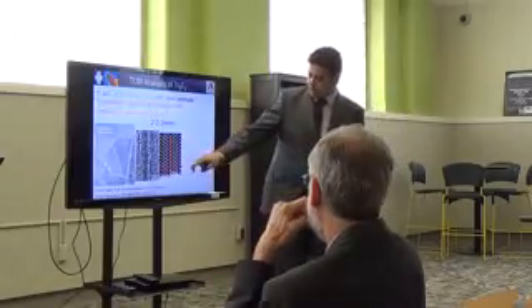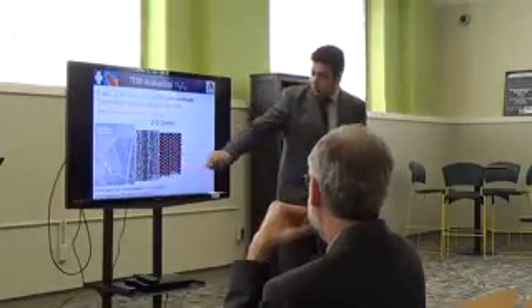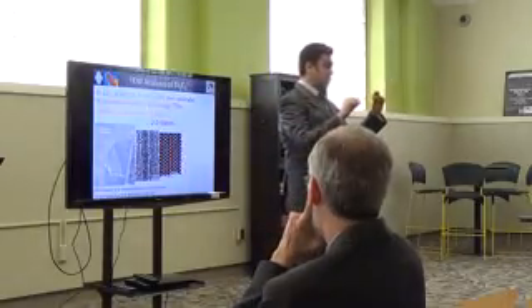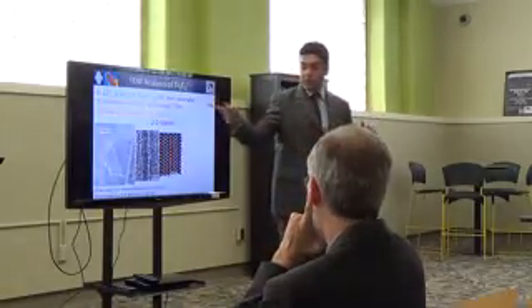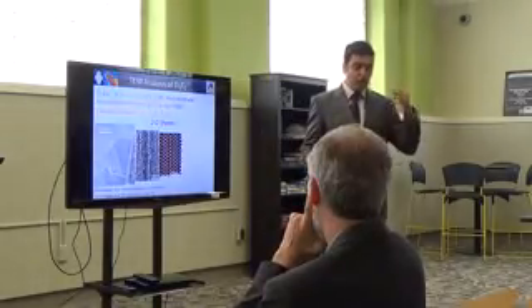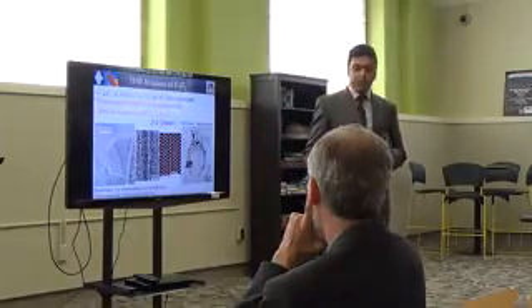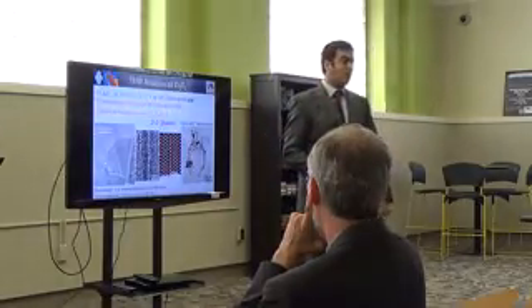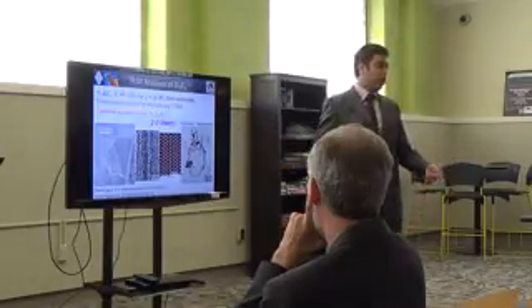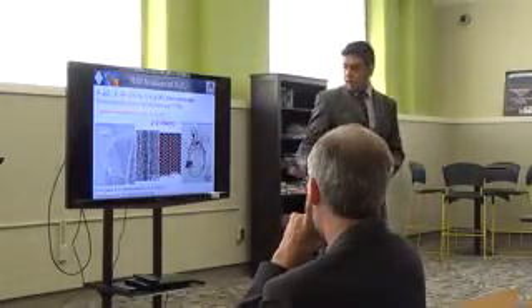And if you look at the cross-section, this is a cross-section for one of those layers. It's actually 2 layers, if you look at the atomic model. Each layer consists of the MXene block, which is around 5 atoms in this case, which is titanium 3 carbide 2. We can have it 2 atoms in case of titanium 2 carbide. Sorry, 3 atoms. They were not only electron transparent, but they were also optically transparent. This is a flake of MXene using an optical microscope, in transmission mode, and you can see that they are optically transparent.